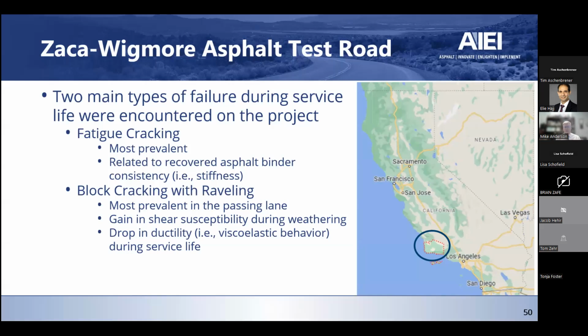But what was interesting about this test road, the 10 different binders they looked at and all that, and this climate, which is Southern California, so thermal cracking is not really what you're worried about so much. But they found fatigue cracking, and they said that was the most prevalent on the project, and it was related to the stiffness of the asphalt binder, the recovered binder consistency. But they also found a secondary distress that was most prevalent in the passing lane, so the lane that was less traveled, had less trafficking, and that was block cracking with raveling, and they found that was related to a gain in shear susceptibility during weathering or a drop in ductility during service life. In other words, as the material became more brittle, they saw more of this block cracking with raveling.